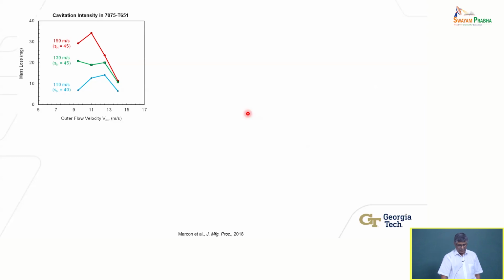So mass loss is a metric that is used. There are ASTM standards that tell you that for cavitation you can use mass loss. Okay, mass loss is how much, instead of peening, we are eroding. I expose the surface to an extended period of time, I erode material, I see how much material I eroded. Obviously, if the cavitation is stronger, I should erode more. There should be more mass loss, right, intuitively. Which would mean that, hey, if I don't expose it for that long, I should be able to generate more residual stresses quicker, right? The same idea applies.